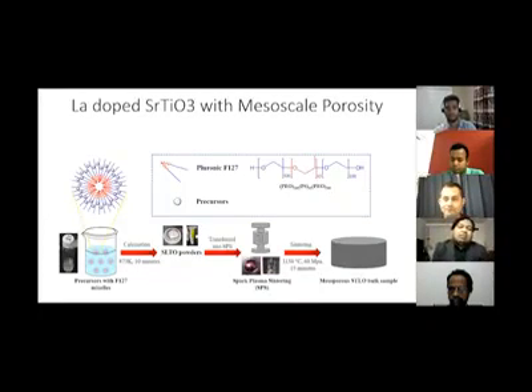So we use a chemical process and add a polymeric micelle assembly method to introduce the porosity in our powder, and then we do SPS, spark plasma sintering, on that powder. So we get the bulk sample, and the beauty is that it is still bulk, but it has some porosities in the nanoscale.